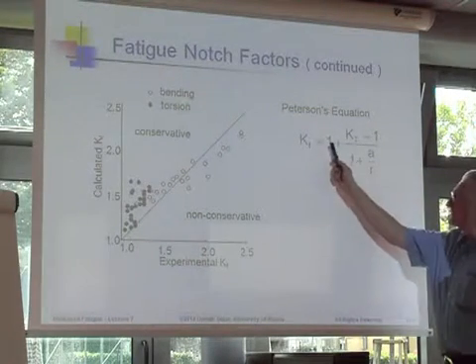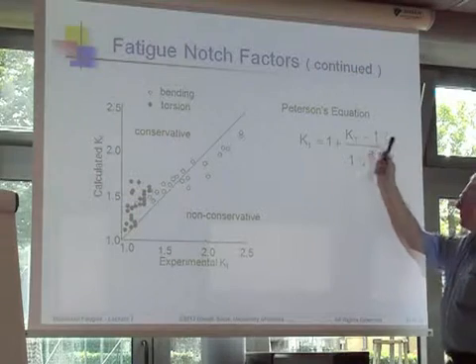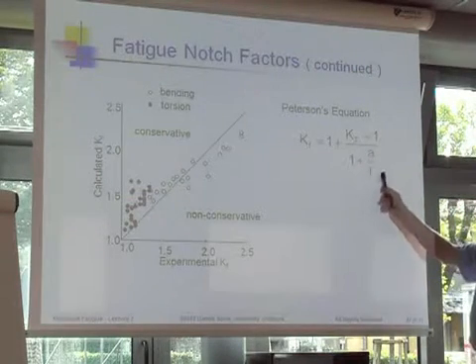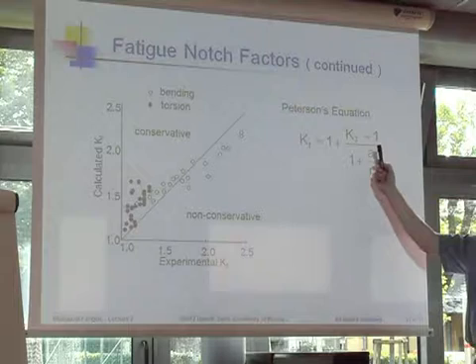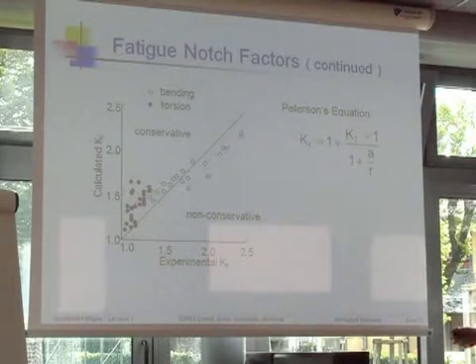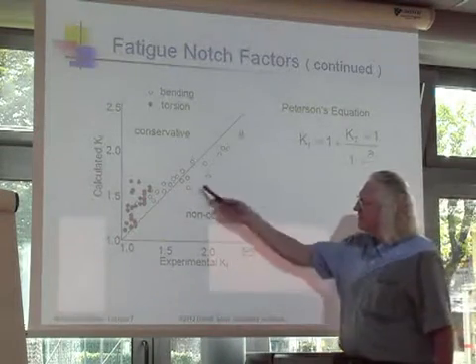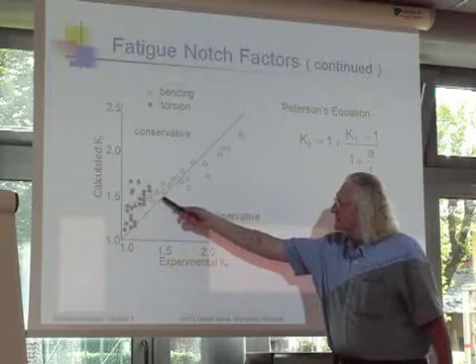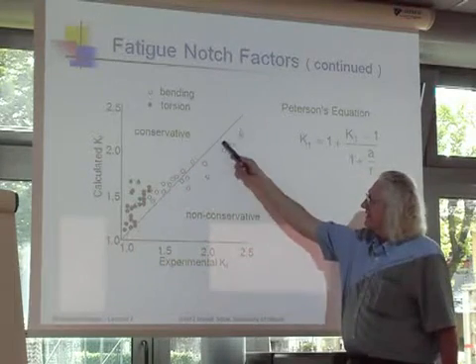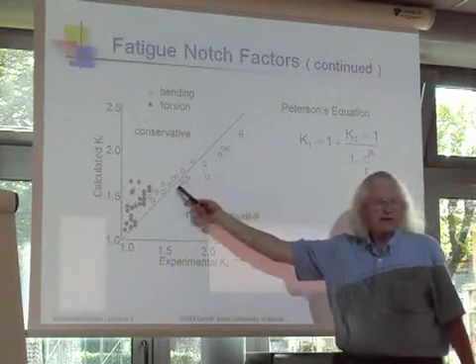The effective stress concentration is 1 plus (K_t minus 1) over (1 plus A over R), and A is this mosaic block size. Okay? And if you try this in bending, since people have been doing it for 100 years, you can see there's a pretty reasonable correlation between this calculated KF and the experimental KF.